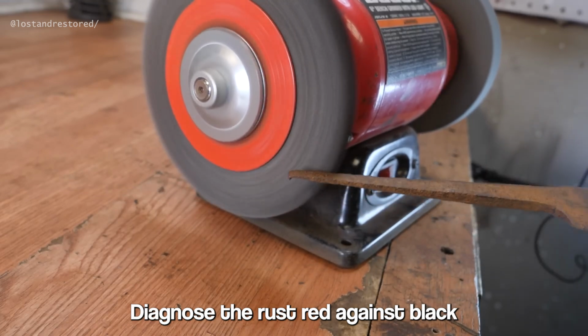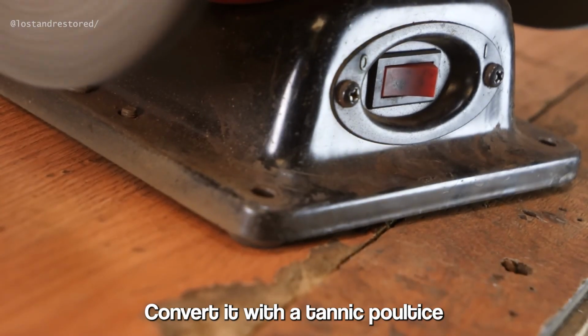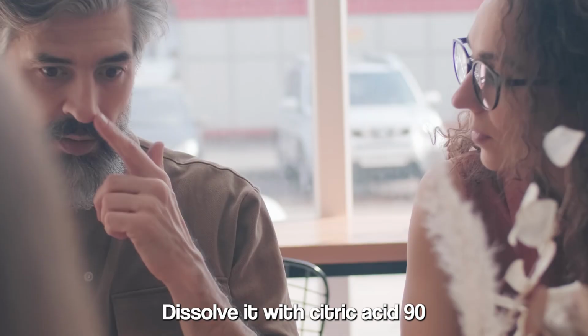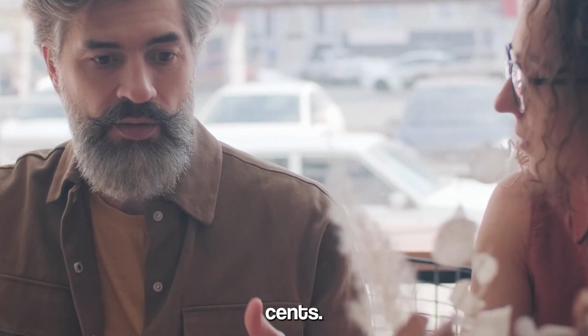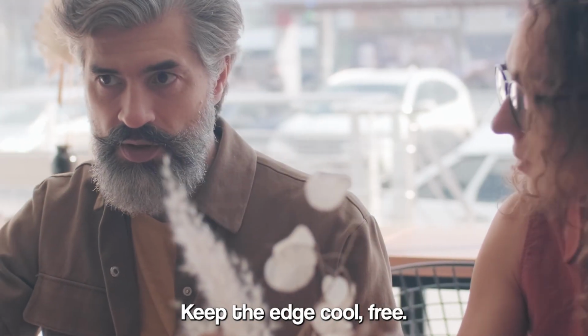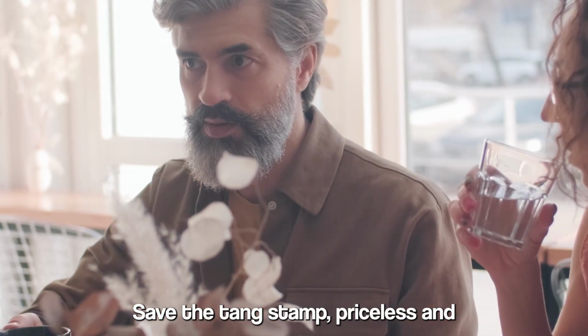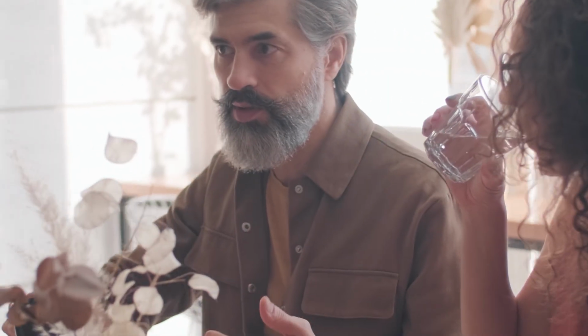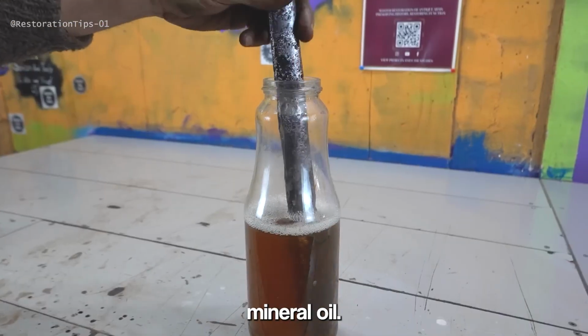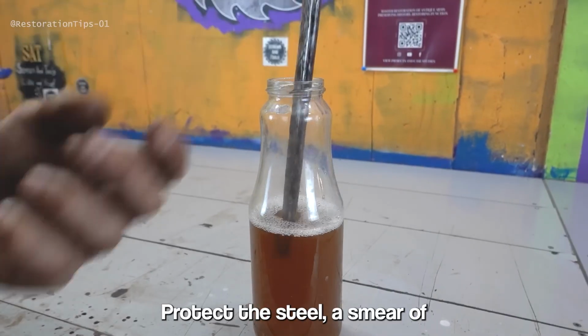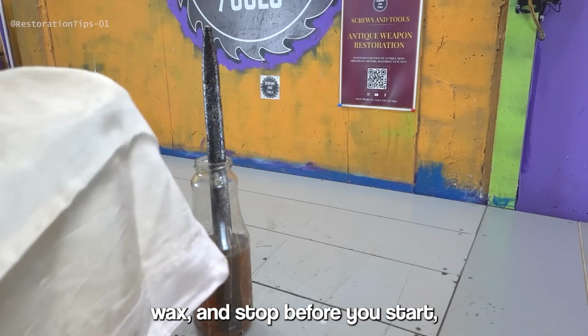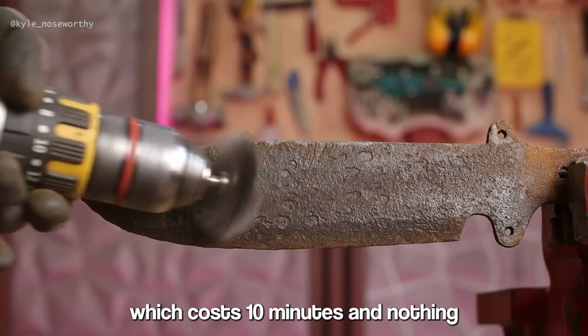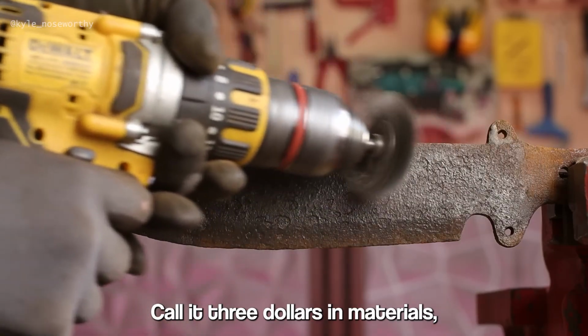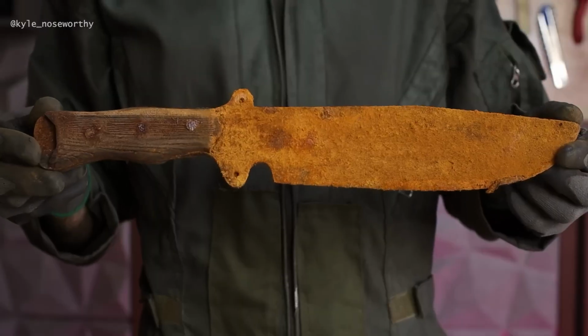Diagnose the rust, red against black, for nothing. Convert it with a tannic poultice, a couple of dollars. Dissolve it with citric acid, 90 cents. Keep the edge cool, free. Save the tang stamp, priceless and gone in one pass. Oil the bone, $1 of mineral oil. Protect the steel, a smear of wax. And stop before you start, which costs 10 minutes and nothing else. Call it $3 in materials, all in.